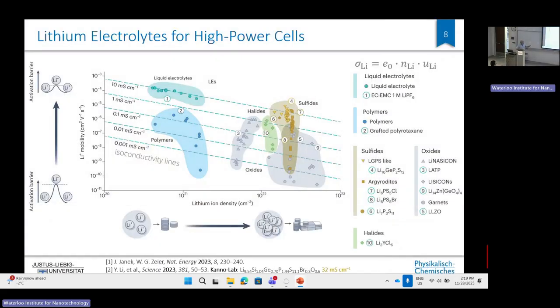This graph is something we felt motivated to make by semiconductor physics, where semiconductors are often analyzed by plotting charge carrier density. Here it is the lithium ion density, the number density of ions per cubic centimeter, versus lithium mobility, the electrical mobility, as you would also look for electron or hole mobility in a semiconductor. The product of the particle density, the concentration, times the mobility times the elementary charge gives you the electrical, or in this case, the ionic conductivity of the material. So these green dotted lines are isoconductivity lines. To make that story short, in order to have enough conductivity in your electrolyte to enable high power cells and to be competitive with liquid electrolytes, you have to achieve this 10 millisiemens per centimeter line.